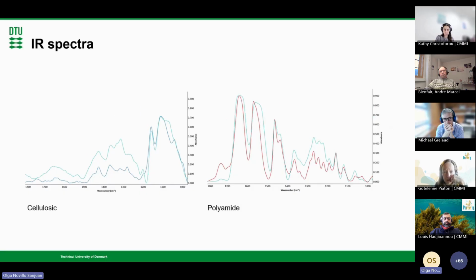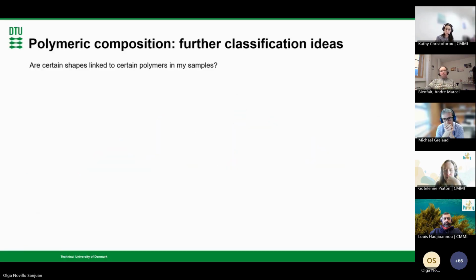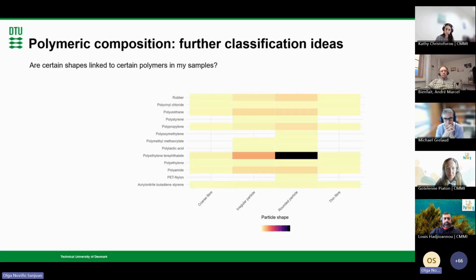These are more examples. This is from natural materials that are very often found in our samples and also in our blanks because they are everywhere. And then you can be creative, and with all this data, you can, for example, see if the shapes in your samples are linked to certain polymers. This is an example of normally no correlation really, but for example in PET we did get that PET was mostly rounded particles and not irregular, so they were quite perfect in a sense.